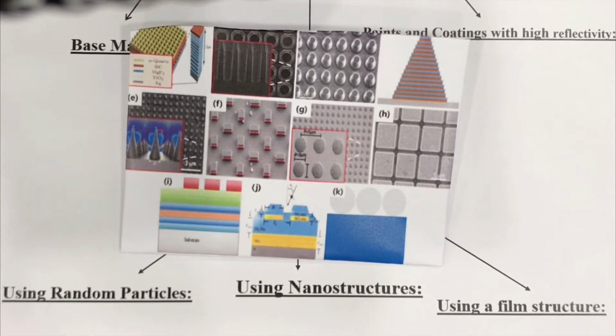group of researchers used this space to build a silicon dioxide photonic crystal absorber which could be used as a radiative cooler. Silicon dioxide was chosen because it exhibits a strong phonon polariton resonance in the atmospheric window region. The absorber was a square lattice photonic crystal with periodicity of 6 micrometers, made up by etching 10 micrometers deep air holes into a double-sided 500 micrometer polished fused silica wafer. When placed under direct sunlight, this device managed to reduce the temperature by 13 Celsius from the ambient temperature.